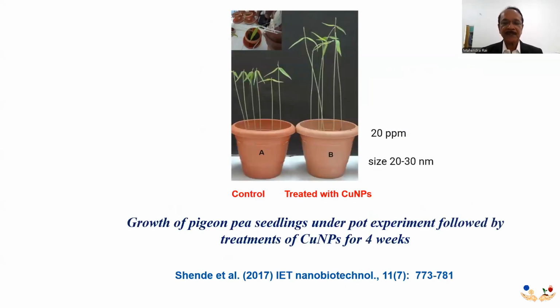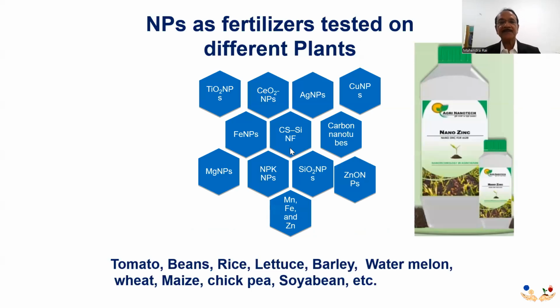We also experimented in pea seedlings. These are pigeon peas, which are common in India and used in vegetables and food. These pea seedlings were grown from seeds treated with 20 ppm nanoparticles of 20 to 30 nanometers. It was found that the plants treated with copper nanoparticles were taller than the untreated plants.